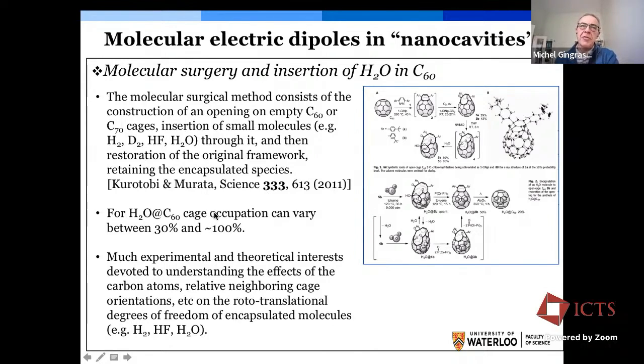And so the water molecule in the gas phase has an electric dipole moment of about 1.8 Debye. This is an energy scale in the hundreds of Kelvin for water molecules separated by a few angstrom. So you immediately see the idea here is that one gets dipole energy scales which are boosted by 2 orders of magnitude compared to magnetic dipole interactions in the context of magnetism. So there's been a huge amount of experimental and theoretical interest devoted to understanding the effects of the carbon atoms in the C60 molecules on the rotational and translational degrees of freedom of encapsulated molecules.